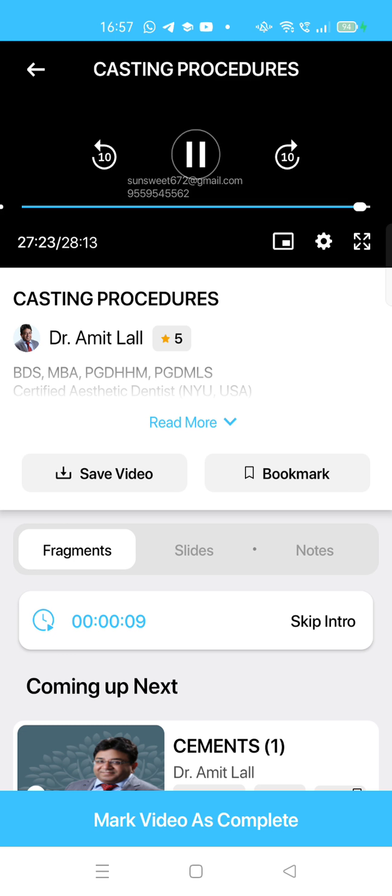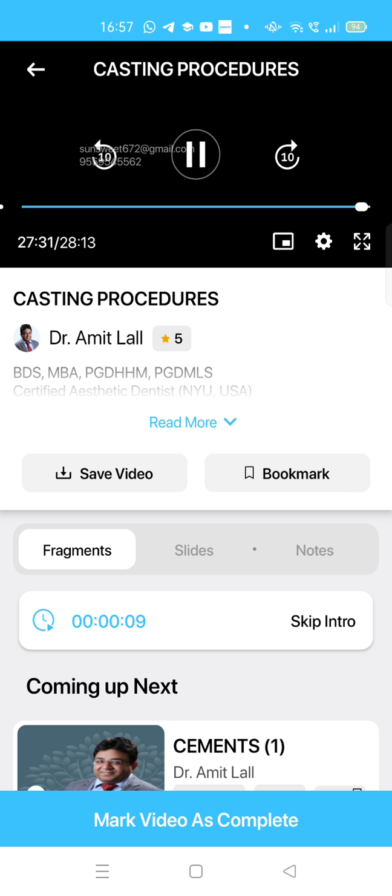Okay, and last in the defects was incomplete casting. First we have rounded and incomplete margins. It is because of insufficient casting pressure. Then second is rounded and shiny margins. The moment you see the word shiny, just remember incomplete wax elimination.